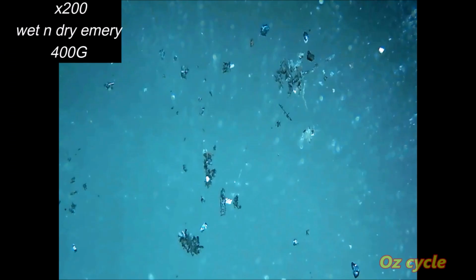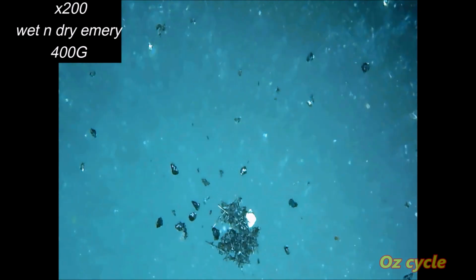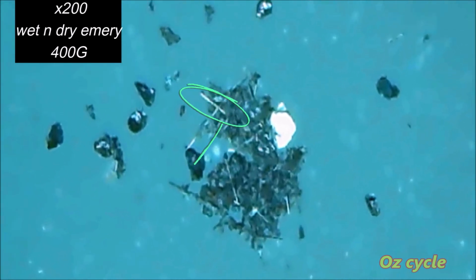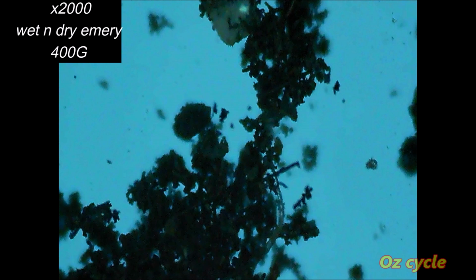Over to the wet and dry emery 400 grit, and you can see the silicon carbide or corundite, which is the abrasive composite which comes off the emery as you sand the carbon fibre. Difficult to detect any carbon splinters in this picture, but we'll go over to this picture, zoom in, and you can definitely see there they are, carbon splinters. And at 2000 magnification we can see a few splinters in this picture.